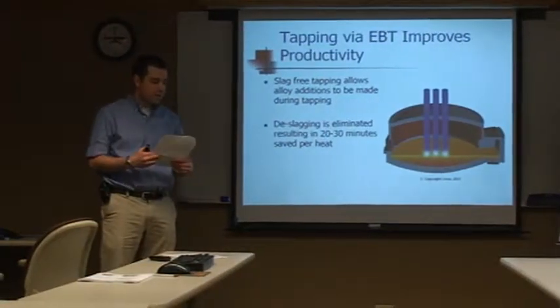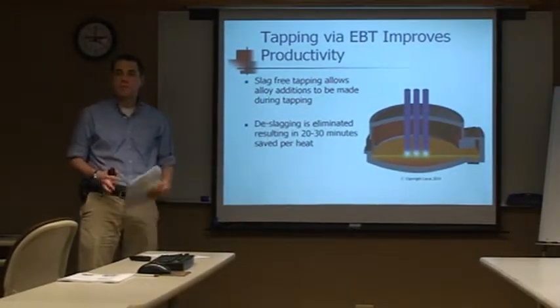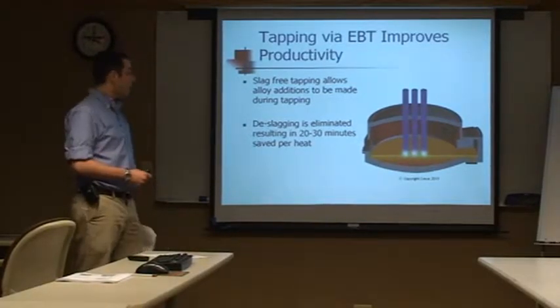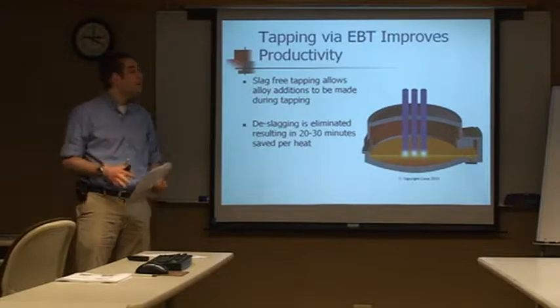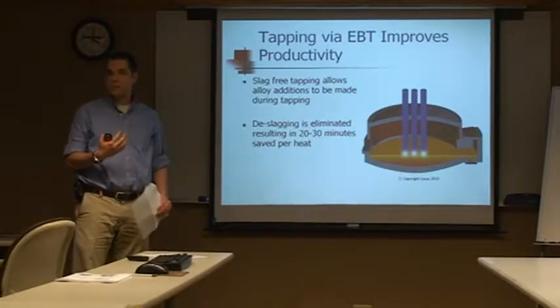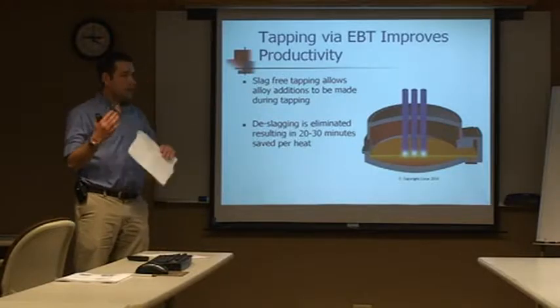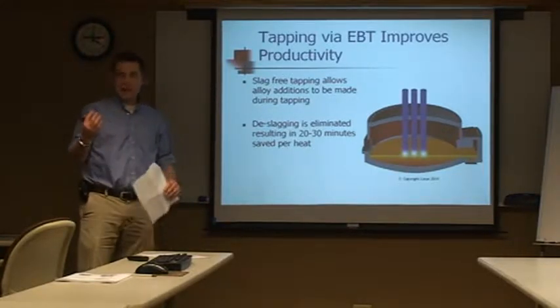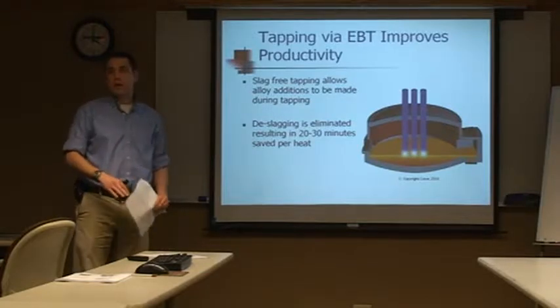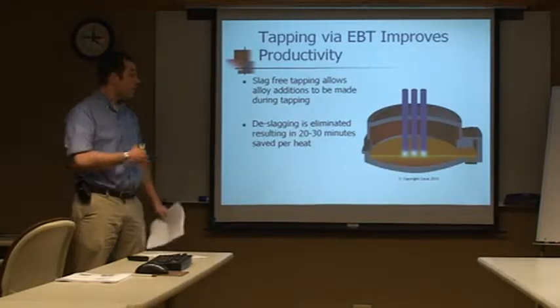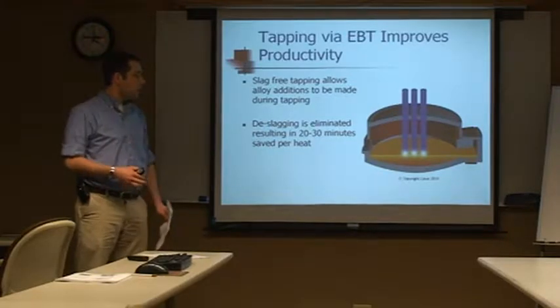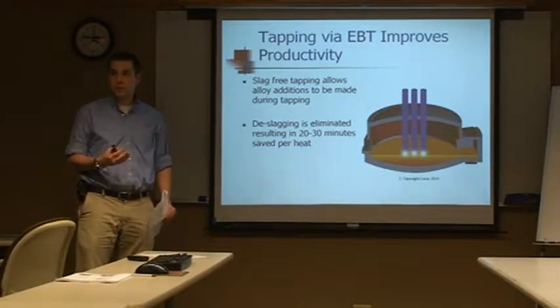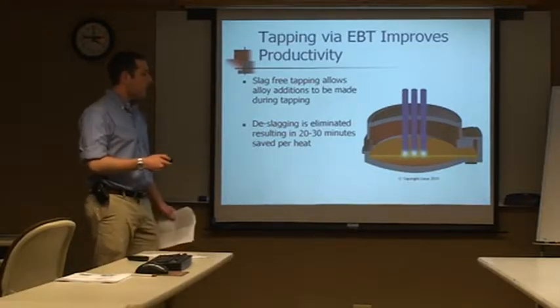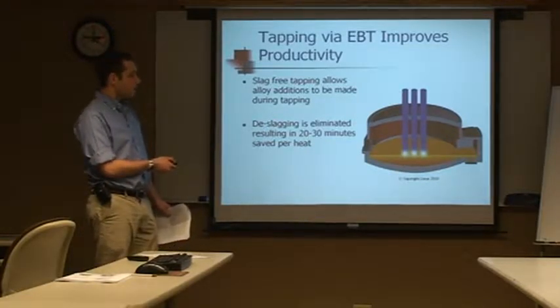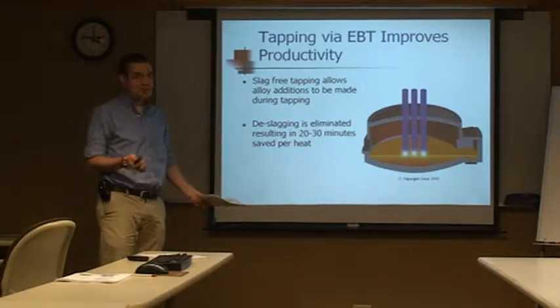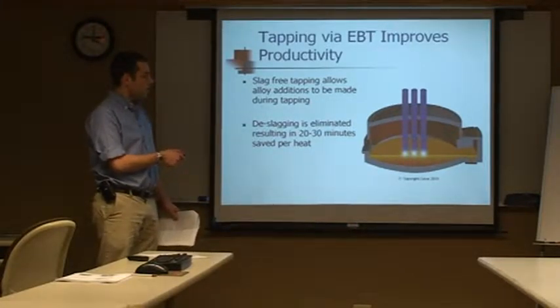So once we have the liquid steel to a level where the carbon and phosphorus levels are where we'd like them, we're ready to pour the steel out into a ladle. Traditionally, this was done via a spout on the arc furnace, and you would tip the arc furnace like a tea kettle and pour out the steel into a ladle. But a lot of the newer arc furnaces, including the one we have at EQS, have an eccentric bottom tapping feature, or EBT, which is where we have our spout at the bottom of the furnace, but it's off-center, or eccentric, and we take the steel out from the bottom.